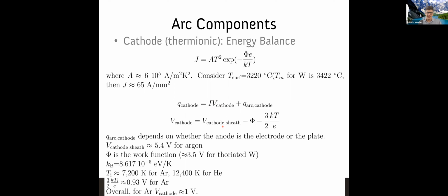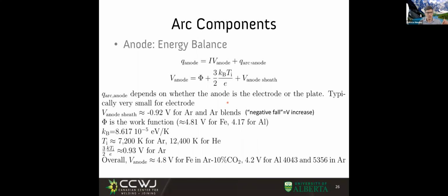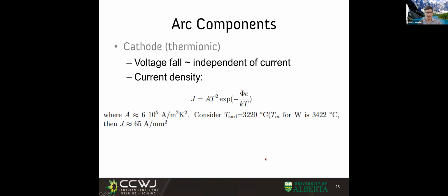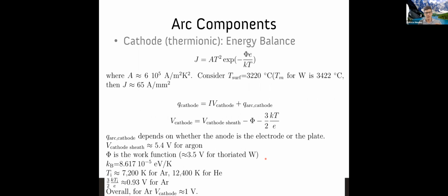The end result is a thermionic cathode, such as in TIG. The fall voltage of the cathode in the tungsten is of the order of 1 volt, give or take. They're not good measurements for those, but if you put 1 volt, you can reproduce many of the things we see, right? Now, compare this with the anode fall voltage that was of the order of 4.8 or 4.2, right? The anode generates about 4.5 volts times current, generates quite a bit of energy, and the thermionic cathode, little energy.